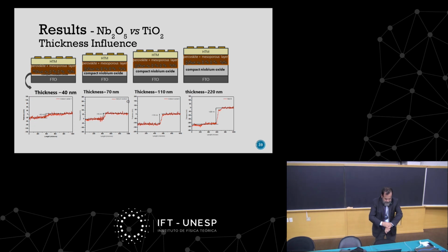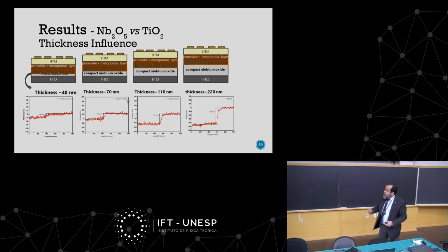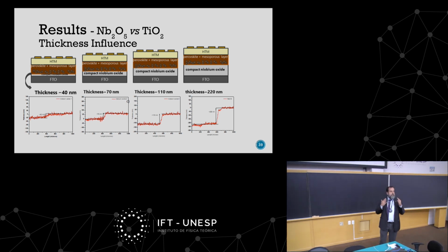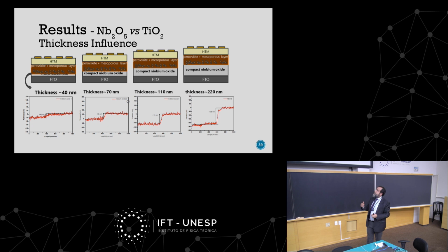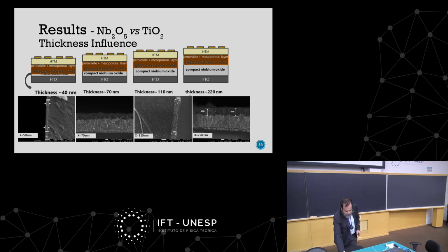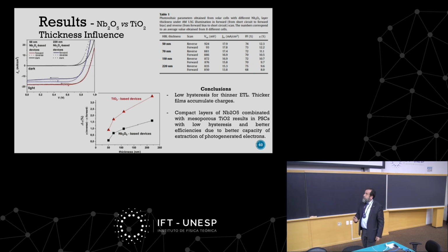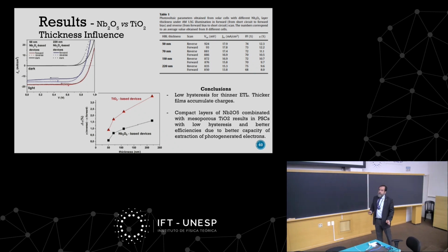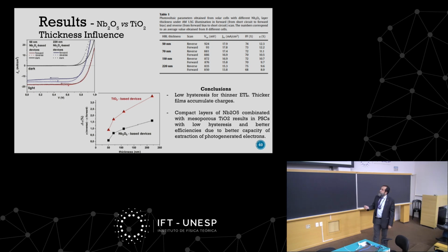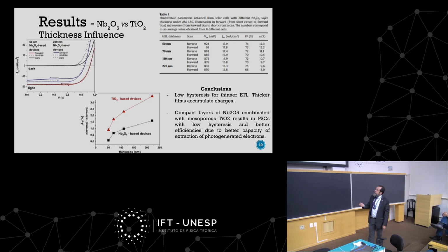Okay? So since time is running up, well, of course, that as a material scientist, we have to do a lot of experiments. So we did what were the effect, for example, of different thicknesses, how this influences. I'm not going into too much of detail, but there is a clear dependence. So this result I told you was for an optimized thickness. So if I have a very thick niobium layer, I do see hysteresis. This is a way of measuring hysteresis. So I do have hysteresis. And the same effect is seen in the TiO2. So we have to optimize.